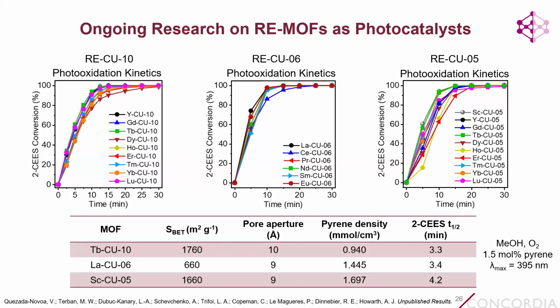And so initially I told you that our hypothesis was that it was a balance between pore aperture size and pyrene density that was most important. But if that were the case, then we would expect that lanthanum Cu-06 and scandium Cu-05 should have faster half-lives than terbium Cu10, because the pore apertures are still quite large, only 1 angstrom smaller, but the density of pyrene chromophores is much higher. So we would expect that we should be able to generate more singlet oxygen from these MOFs. But in fact, these half-lives are, although comparable, a bit slower.